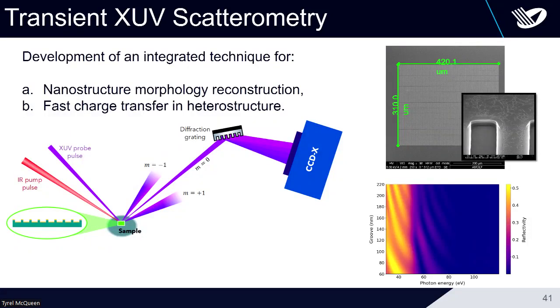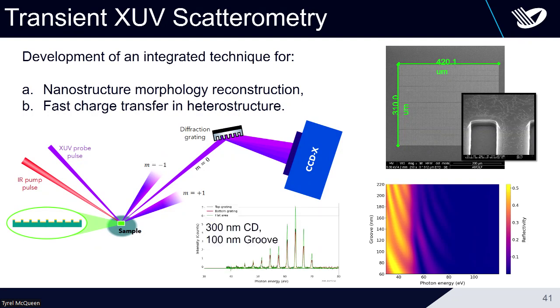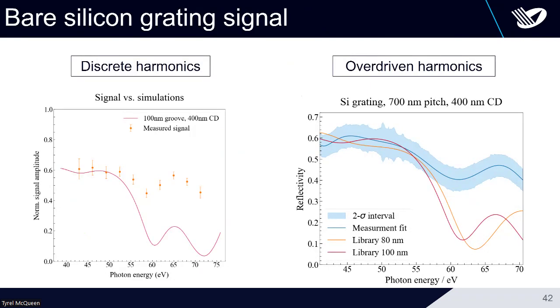The structures we started with, what we already see in the zeroth order, is a simulation. We get a very strong variation of the signal as a function of photon energy for different grating heights. This is basically because we get different interference conditions from the reflected waves at the top and the bottom of the surface. For the measurements, we see both here and here a shape that more or less looks like what we expect for the structure, but there's still quite a bit of discrepancy.